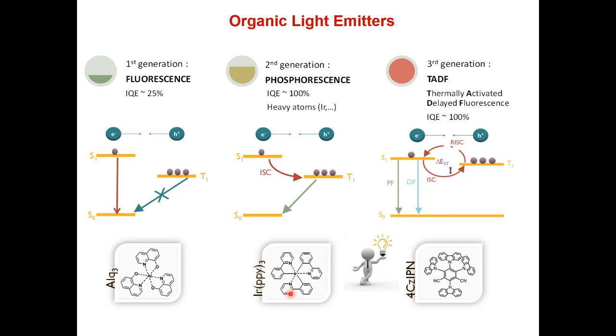I can comment also that the most difficult color to obtain is the blue, because blue is a very high energy for light emission, and this energy can also be used to make photochemistry on the molecule and start degrading it. So there is a big issue, but it's also the same for the LED technology: to make a very good blue emitting material which is stable over many, many hours of operation. So blue is the problem. Maybe this was the question of Stefan. Or if you want to play with crystallochromy, the temperature rise is a problem.